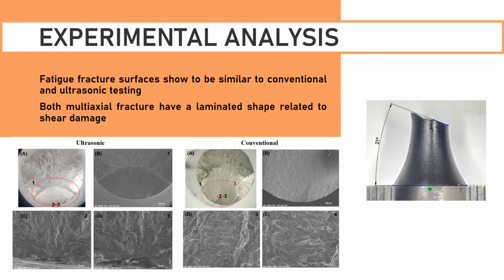Now comparing the multi-axial specimens also tested in conventional and ultrasonic fatigue machines, with in-phase shear and axial stress with von Mises relation, there is an agreement between the fracture angles for both tests, and the initiation point and the propagation also show various similarities. Observing the images presented in this slide, we can clearly see the laminated shape related to shear damage, thus proving the existence of torsional damage in the ultrasonic fatigue machine built.